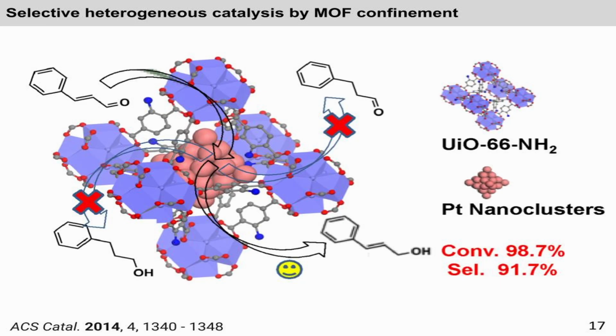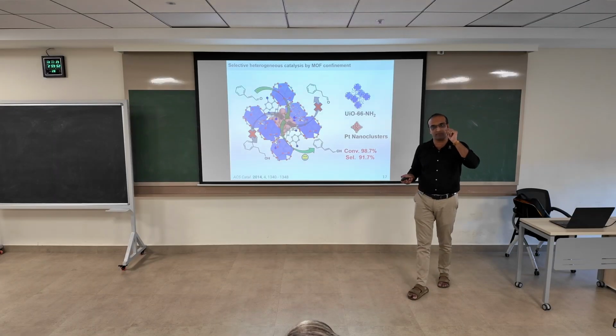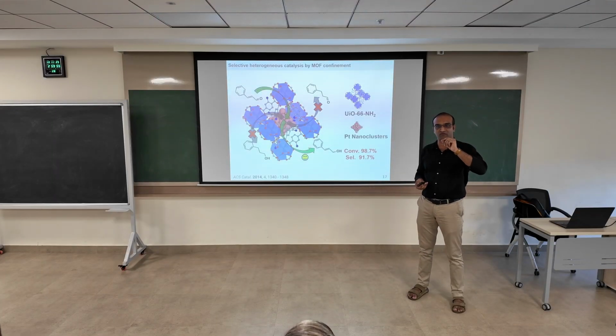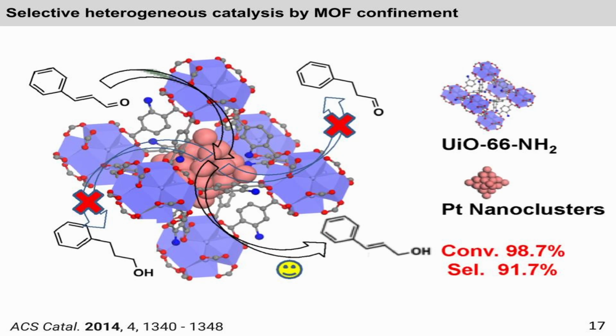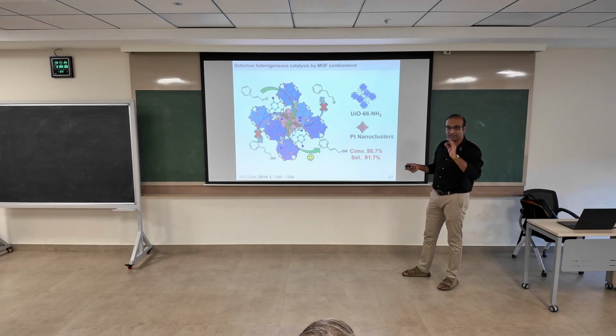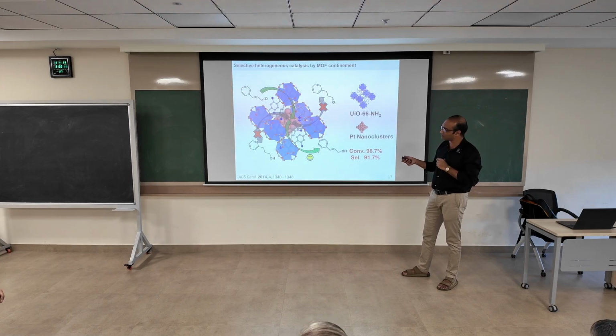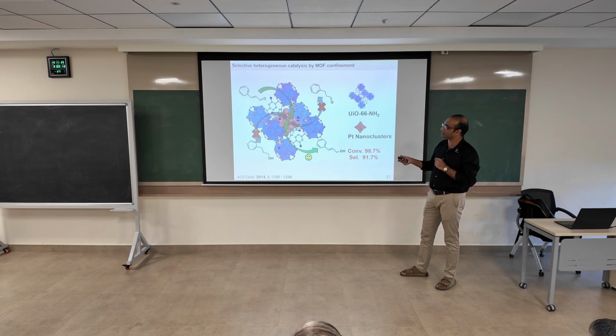We published this paper in 2014. So here, by controlling the place where the platinum nanocluster is within the MOF, you can restrict the access of all the bonds of this particular molecule, this cinnamaldehyde. You have a double bond here and you have a carbonyl bond. Typically the value in industry for most of these alpha beta unsaturated aldehydes is that we only want to get this converted to hydroxyl group, okay?